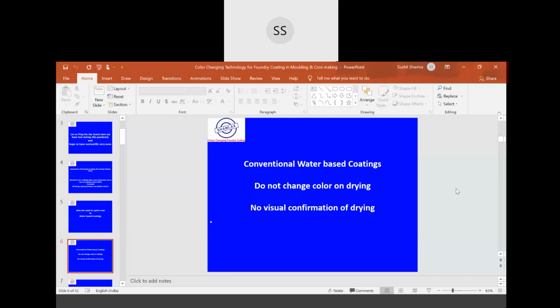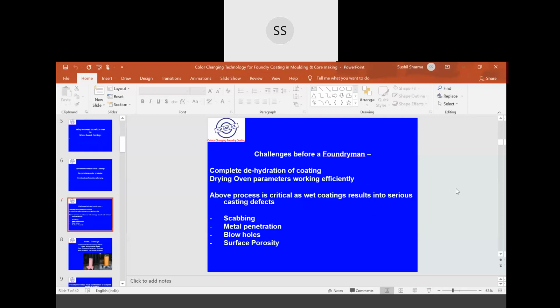And the challenge, as I already told you, is visual confirmation of drying. In case of white coatings or any other colored coatings, the color after drying remains the same, and there is no visual confirmation for the foundryman to understand whether the coating has dried or not. And they try to dry it with the help of a torch or use different methods like industrial ovens to dry the pores. As I told you, complete dehydration of the coating, drying parameters working efficiently or not, is one of the biggest challenges.